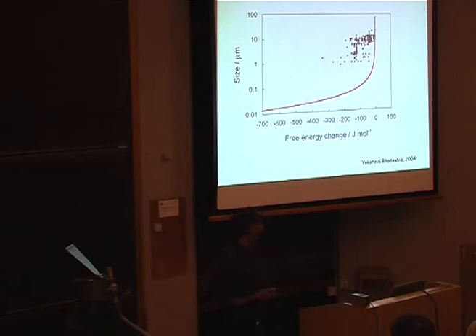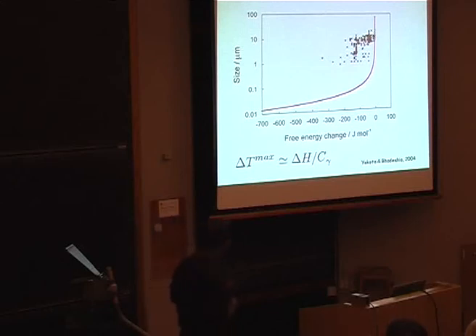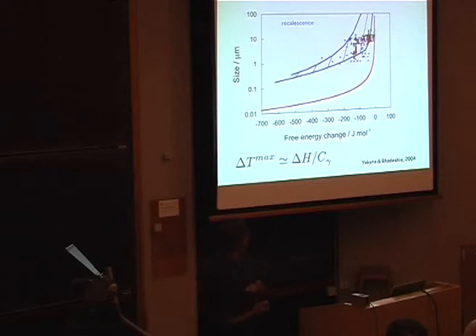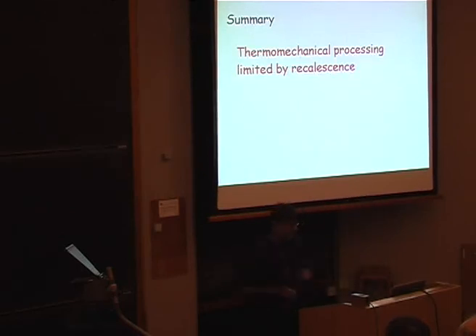The reason for this is that when you do a phase change at a very high undercooling, you get a lot of enthalpy released, and that heats up the material. So that's a phenomenon known as recalescence. So the enthalpy change actually heats up your material. And when you take account of that recalescence, you predict that you're not going to get much smaller than 1 micrometer using the most severe of thermomechanical processes. So this is not going to help us. Thermomechanical processing is limited by recalescence.